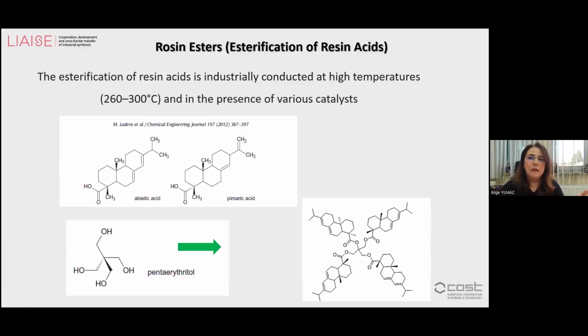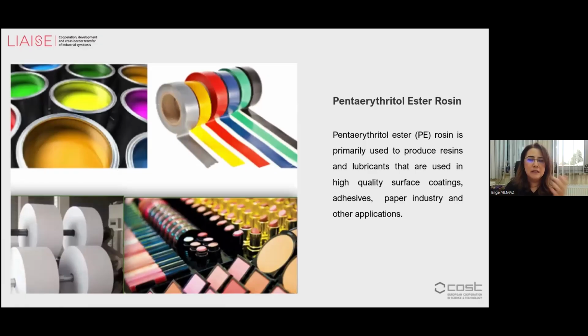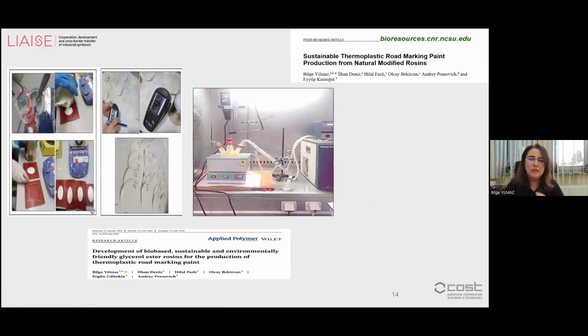In our lab, we can produce rosin esters, especially pentaerythritol esters. We use pentaerythritol and abietic acid at very high centigrade degrees in an inert atmosphere, using various catalysts, and we can produce these structures, for example. These esters can easily be used especially in thermoplastic road markings and surface coating, paper industry, adhesives, and other applications. And we have some papers about